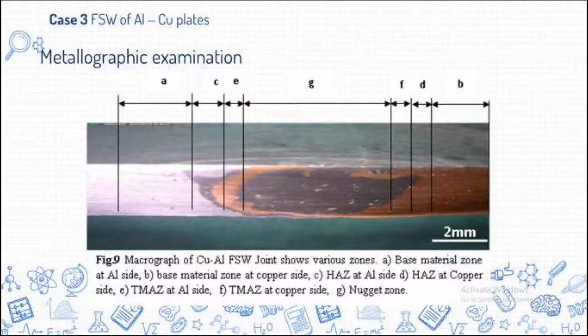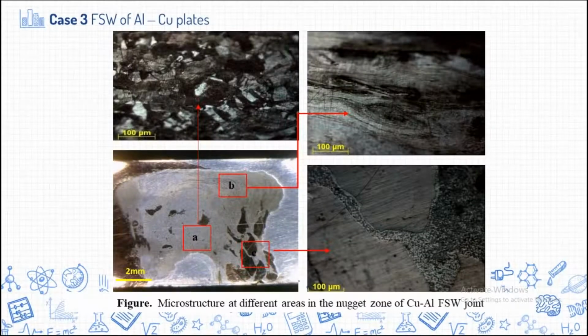And what about the center of the welding, the nugget zone microstructure observed for a few samples? This is the nugget zone at the center of the welding, and it looks somewhat like copper and aluminum are homogeneously mixed over here, and there are some lines observed over here. We wanted to know what these lines could be, and this can be observed over here, like this material movement or mixing takes place over here like this.